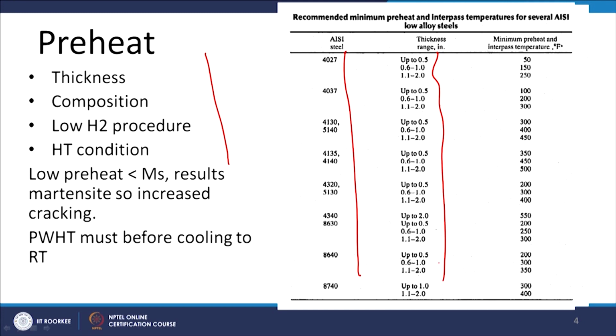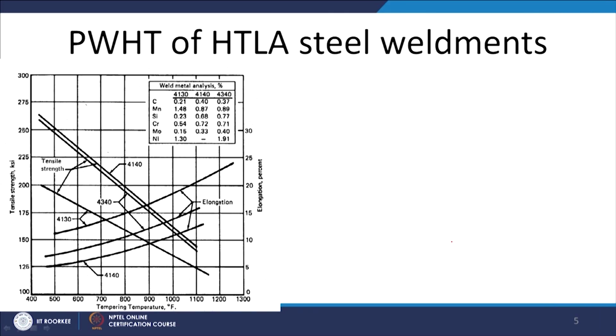So, like say for the different grades of the heat treatable alloy steels, and for different thicknesses in inch, we know that the higher the thickness, the greater the preheat temperature that we need to use, changing from 50 to 250. And likewise, increasing the carbon equivalent will be leading to the use of higher preheat and interpass temperatures. So, greater the thickness, greater the preheat temperature, greater the carbon equivalent, higher will be the preheat temperature. So, this is how we can choose, and we know that the preheat temperature we have chosen will be dictating the cooling rate, and accordingly we will be having the martensite, bainite, perlite, ferrite in the weld joint.